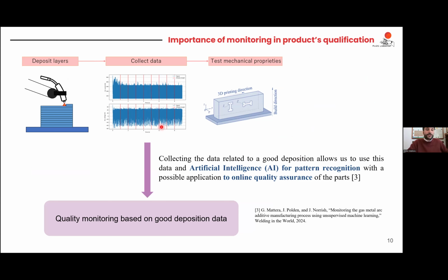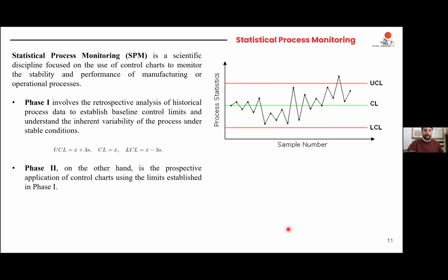And the data collection part, which is mandated by the ISO standards, is a really important data source for artificial intelligence. Because at the end, you can use the good deposition data that you collected during the qualification procedure and use artificial intelligence for pattern recognition of good deposition data, and then just develop an application that is able to tell you if what you're building up is in line with what you observed during the qualification procedure. So you are monitoring versus the good deposition data.